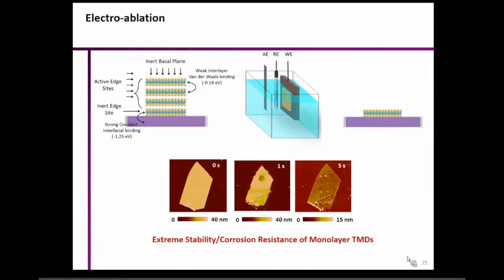What we believe is that when you exfoliate these 2D materials on a substrate, the layers lying on the top are connected by van der Waals force, right? So this is a very weak force, and the energy is generally of the order of 0.16 eV. But because of the exfoliation process, there is some interaction that takes place between the substrate and the 2D material, which is much stronger. And these are some calculations done by my colleagues from the Oak Ridge National Lab.